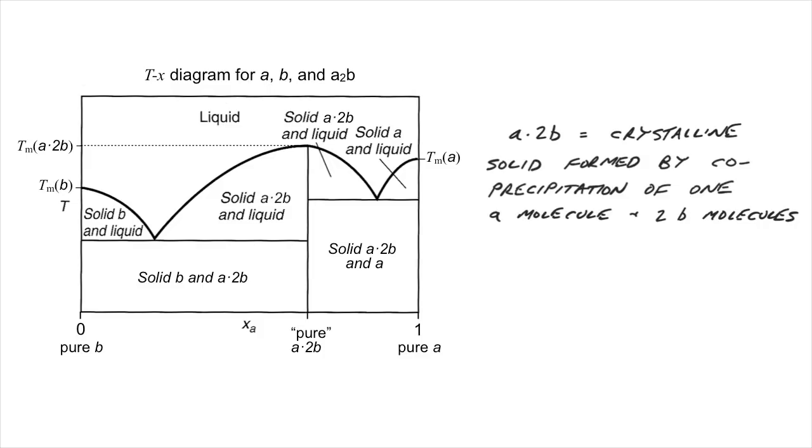An interesting situation that often occurs in solids is co-precipitation of two or more species in a single ordered crystal, such as a salt hydrate or other ordered phase with a distinct ratio of atoms or molecules. Such crystalline substances constitute their own distinct line phase and can lead to multiple solid-solid and solid-liquid two-phase regions. In such a system, solid mixtures can only vary in composition by changing the relative amounts of the line phases, not by composition variations within each phase.